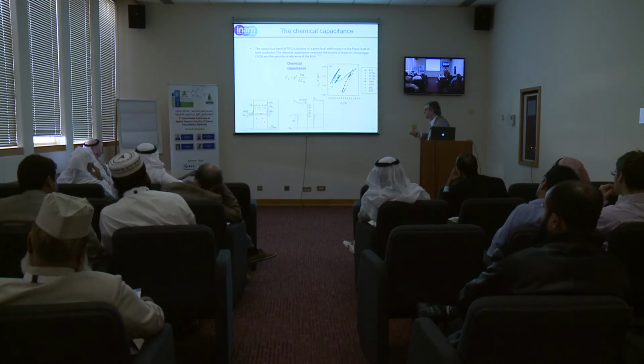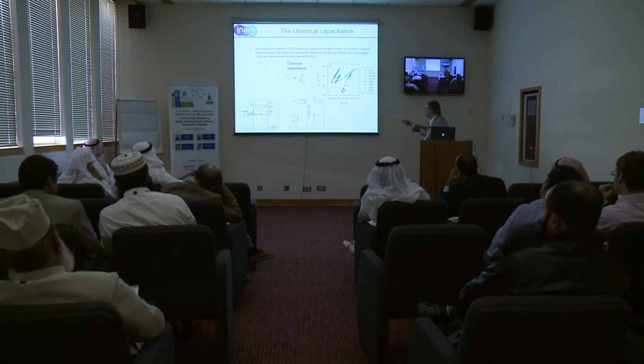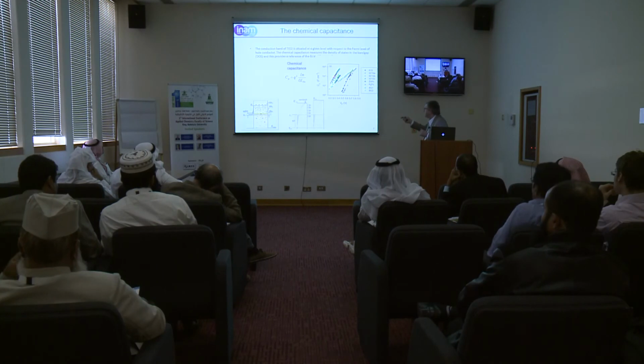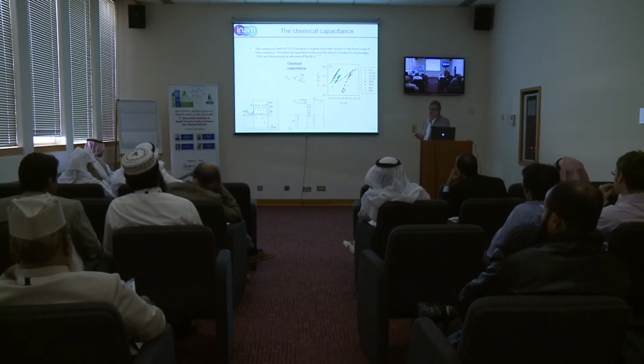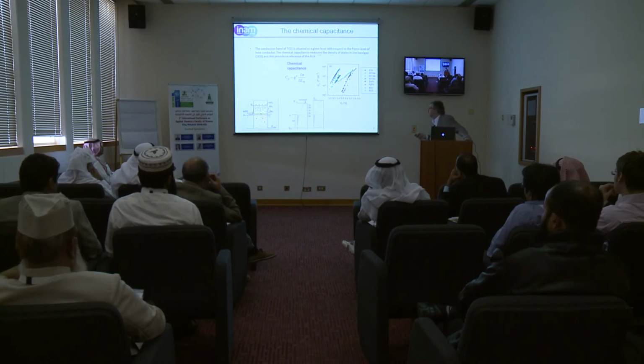For example, if you put a dipole oriented this way, all the levels go down. So at the same voltage, you get more charge density. So you see this shift. This is something essential in order to see the energetics of your titanium dioxide. And this is very important information you can get from this type of analysis.